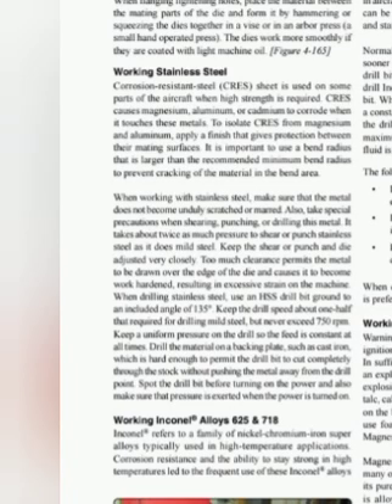When drilling stainless steel, use a HSS drill bit ground to an included angle of 135 degrees. Keep the drill speed about one half that required for drilling mild steel, but never exceed 750 RPM. Keep a uniform pressure on the drill so the feed is constant at all times.